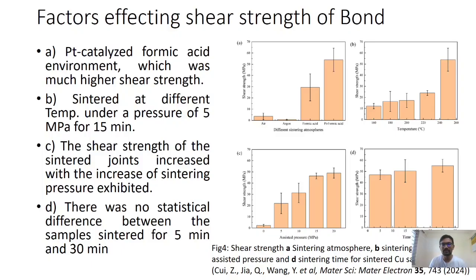Now I will discuss factors affecting shear strength of copper bond. We have four parameters here. First, we will discuss different sintering atmospheres. When we use argon as our sintering atmosphere, we get very little shear strength, about 0.7 megapascal, and in air we get about 5 megapascal, and when we use formic acid we get about 30 megapascal. If we use platinum as catalyst with formic acid as sintering atmosphere, we get shear strength of about 55 megapascals. The reason is that with platinum and formic acid there is formation of hydrogen radicals, and oxide formation is very low, due to which we get high shear strength and a clean surface.